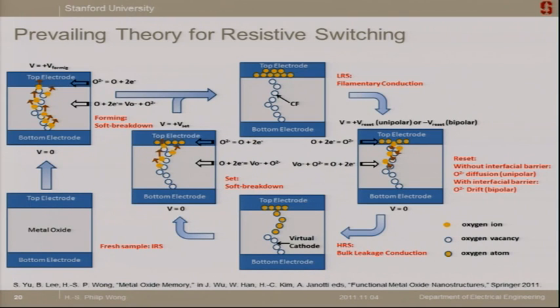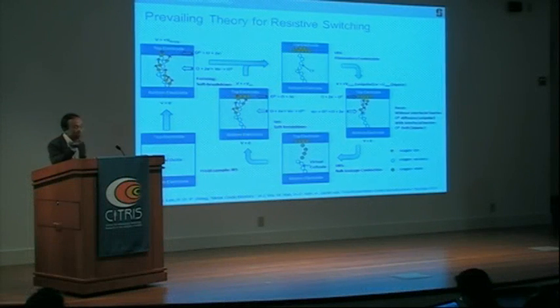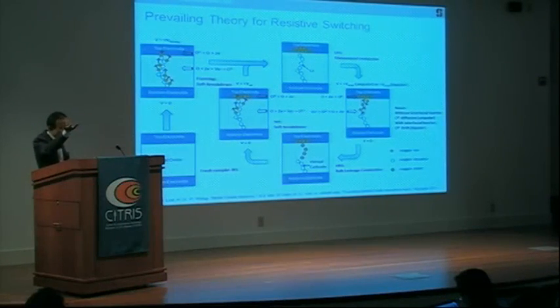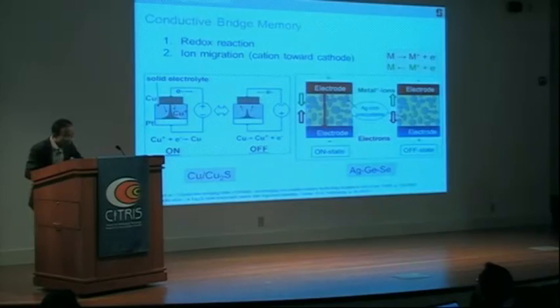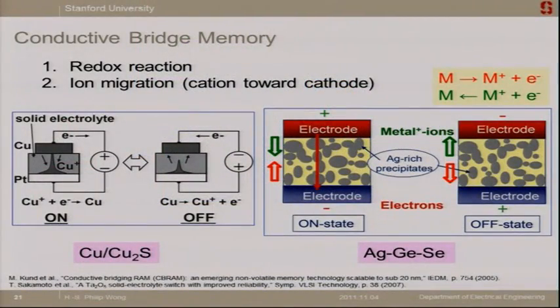But some of the prevailing theory is that through the soft breakdown, you create oxygen vacancies as a conductive filament, which bridges the two electrodes, and the oxygen gets stored in one of the electrodes, for example, in the titanium nitride electrode. And then when you apply the opposite direction, you push the oxygen back down and disrupt the filament, and therefore you can switch between two states. So this is a prevailing theory, but hardly could be considered well accepted or well proven. So that's the physics of the RRAM.